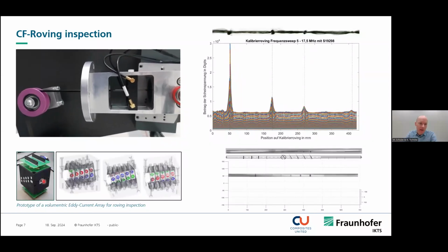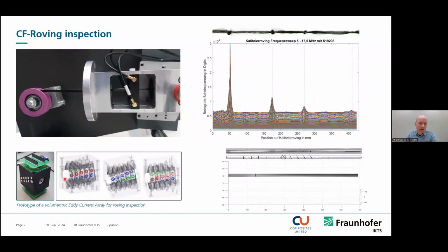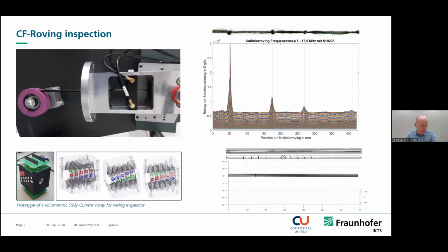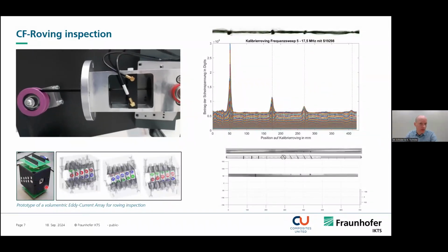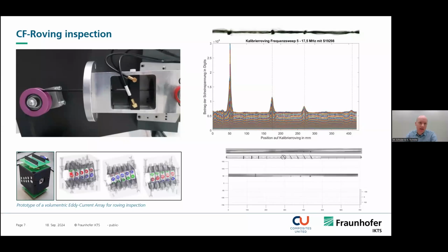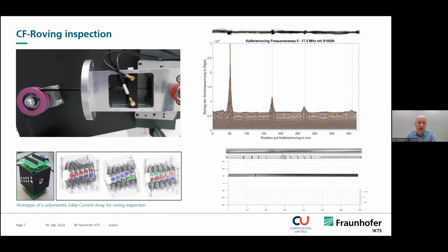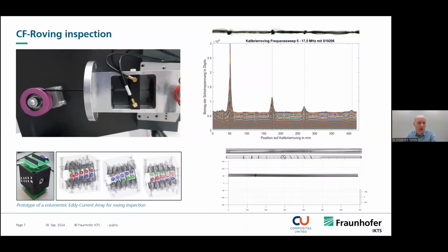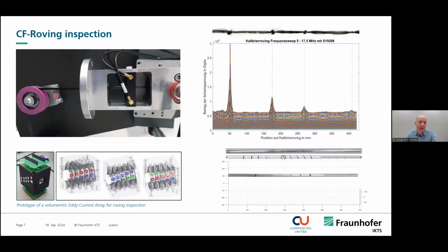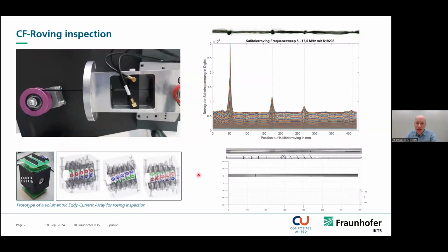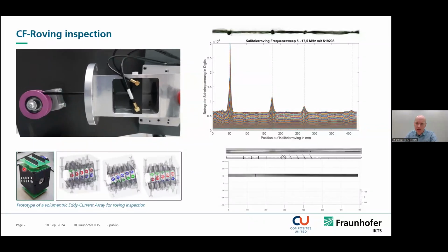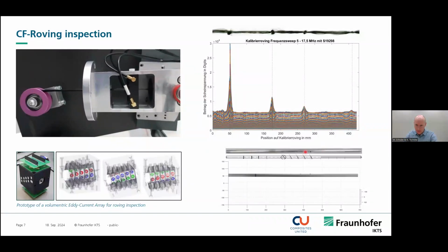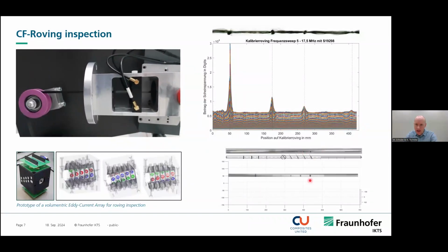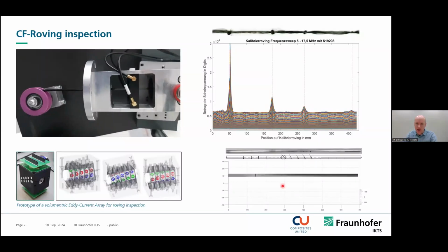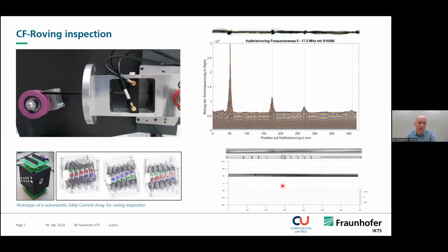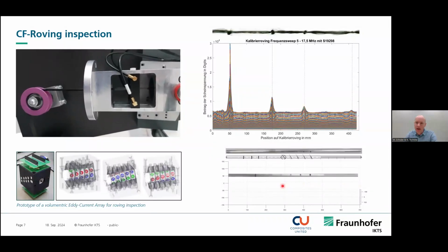And actual developments are these so-called volumetric eddy current arrays. So here we see many coils that surround this tube-based sensor. And by changing the transmitting and receiving configuration, we can generate a volumetric image of the roving. So that's our actual development. And we tested this probe on an aluminum pipe. Here we see some boreholes in the pipe and a rotating image. So we can also generate eddy current 3D scans of such a pipe.